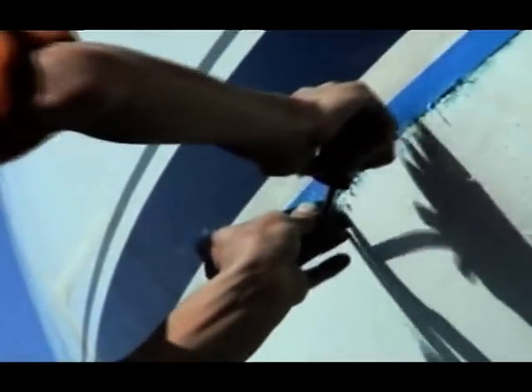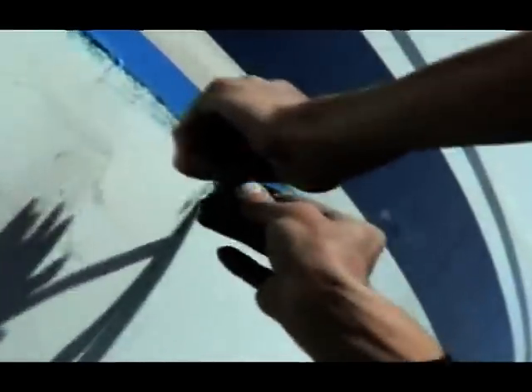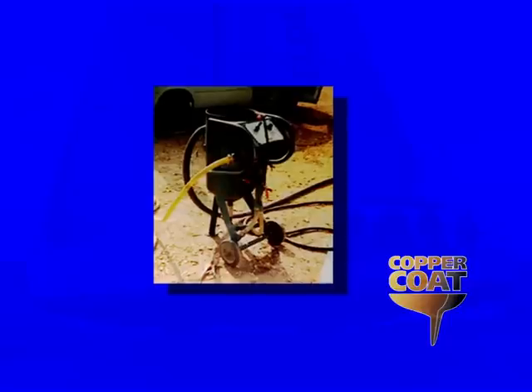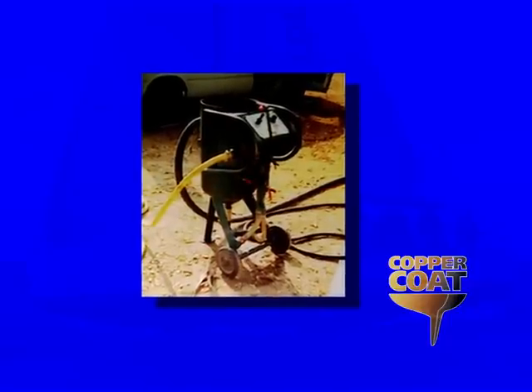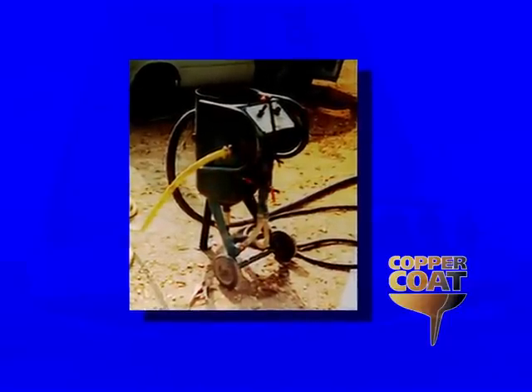As is common with all epoxy coatings, it's important that the surface to be coated is well prepared. All surfaces must be cleaned of all contaminants, including dirt, dust, grease, rust, or loose coatings. Two-pack coatings, including Coppercoat, must only be applied to sound and permanent surfaces, which means that any previously applied coatings of single-pack paint or conventional anti-fouling must be fully removed. The best way to achieve this is to use a low-pressure slurry blast of sand and water, although it's perfectly acceptable to remove old paint by hand, as shown here.